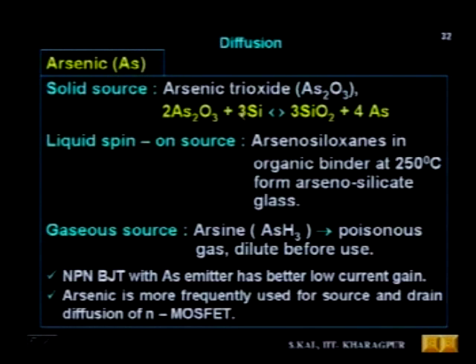You see As2O3 plus 3Si, it will form SiO2 plus 4As at high temperature inside the furnace. This arsenic atom, individual arsenic atom, will diffuse into silicon. That is, solid source is As2O3. Liquid is spin-on source in case of arsenic. Here we don't use bubbler. Just like photoresist to spin, similarly this high viscous liquid spin-on source of arsenic is sprayed over the silicon surface using a spinner, and then it is baked, and then we put the wafer inside the diffusion furnace for arsenic diffusion.